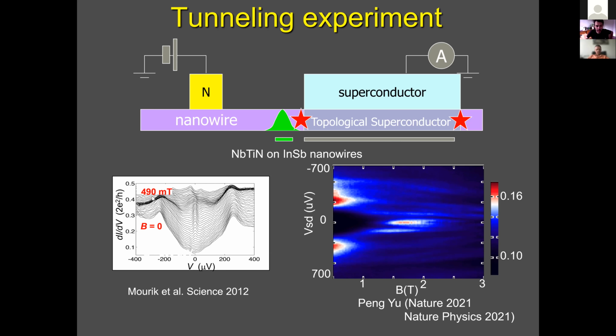Then when we apply magnetic field, all these curves are offset for clarity. After about 100 millitesla, which is quite a significant magnetic field, we start seeing this zero bias peak, and it persists at zero bias, doesn't move from zero bias for a significant range, as expected from a spinless state. It is not sensitive to Zeeman splitting, right? It doesn't Zeeman split.